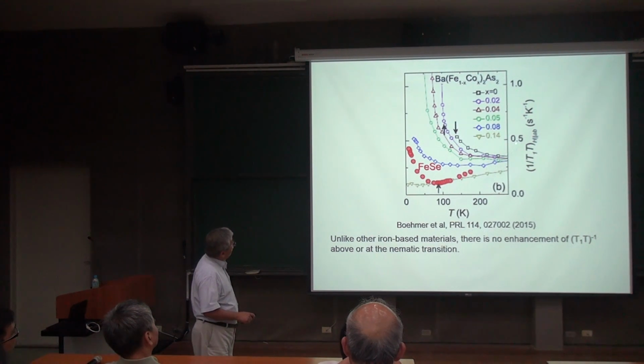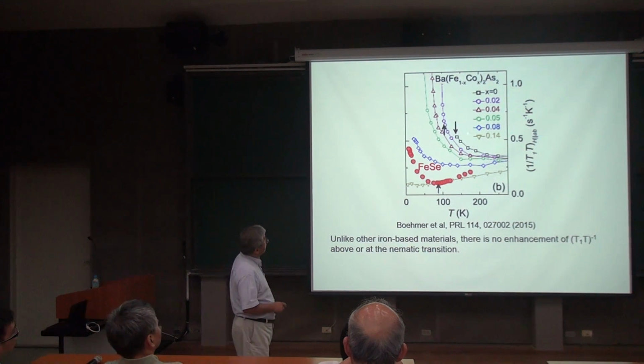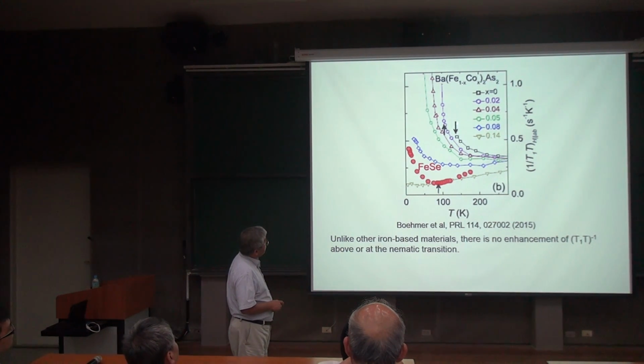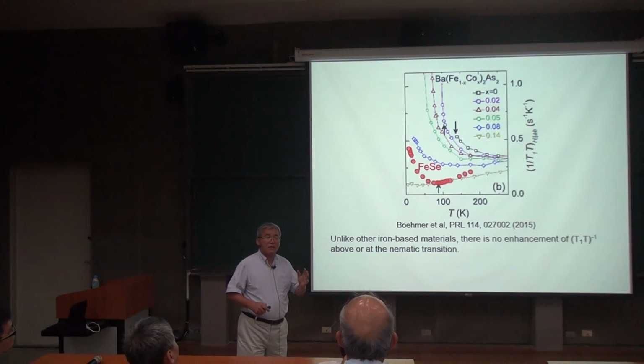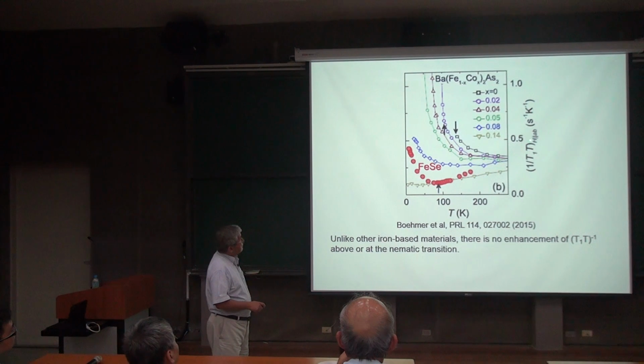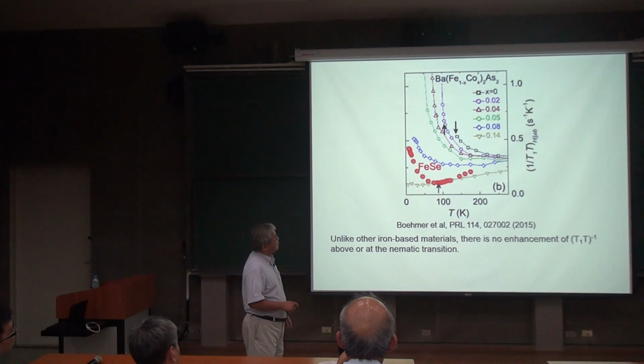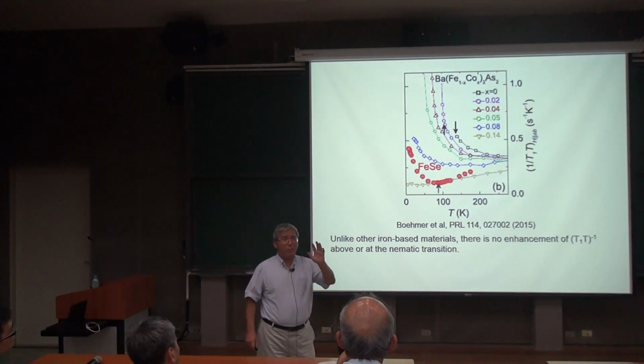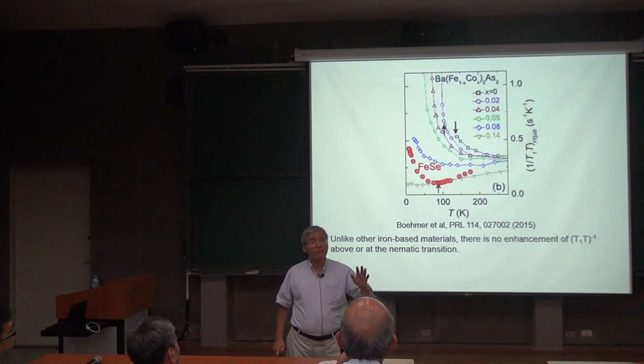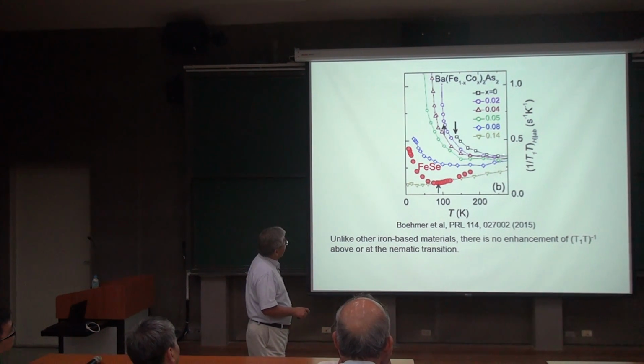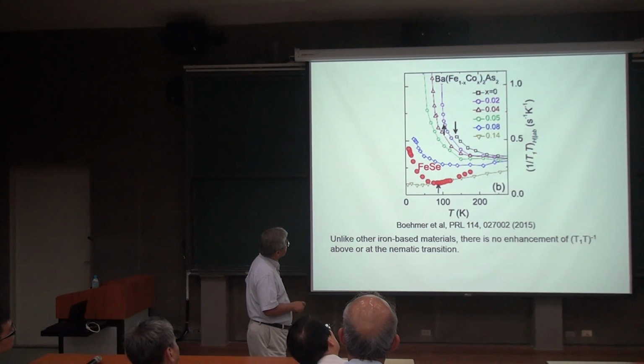So what happened is that for all the iron-based, here, the red circles represent iron selenide, and all the other symbols represent other iron-based superconductors, and this black arrow indicates the temperature at which the system spontaneously distorts. The only thing you need to know is if 1 over T1T is very big, that means the system at low energy has a lot of spin fluctuations. So as you can see, for all the other iron-based superconductors, when the nematic spontaneous structure distortion happens, the 1 over T1T is already substantially enhanced relative to the high temperature state.